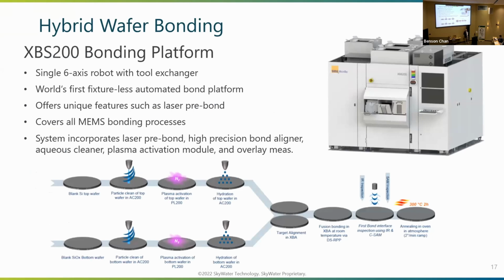We have established a working relationship with SUSS MicroTec, who has an engineering group at our facility down in Florida, and has been instrumental in helping us establish the operation of the XBS200 bonding platform. If you're aware of the process flow that is utilized to exercise this process, it takes a number of different steps to do. You need to do surface preparation by CMP. Those surfaces have to be extraordinarily clean for the yield of that bonding process to be successful. You need to do plasma activation, you need to do hydration processes, you need to do alignment processes, you need to do bonding processes. For a lot of systems, for a lot of users, those processes happen in differentiated equipment sets. For the XBS200, they're all combined into a single platform. So it greatly reduces the time for the process to take place, and it also improves the yield because you're not moving wafers back and forth in your fab between different tools and process modules.